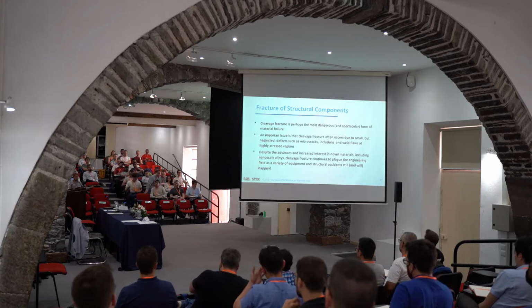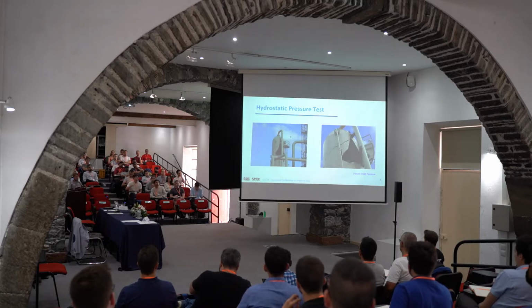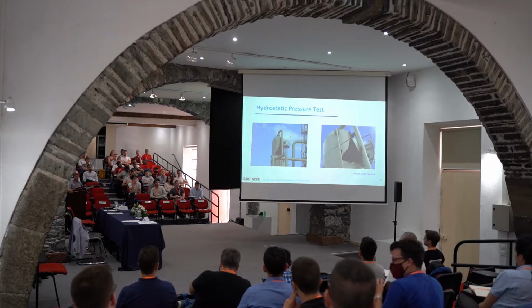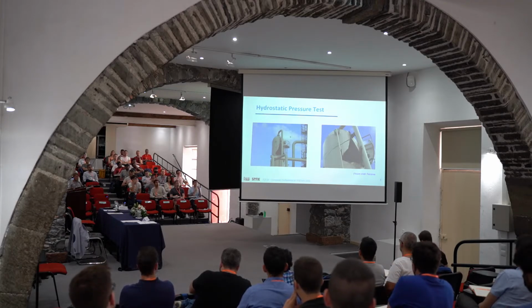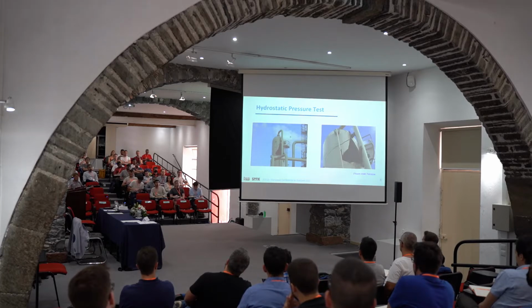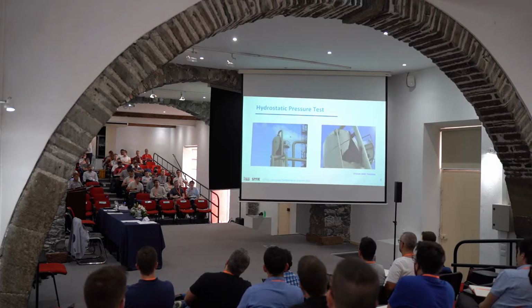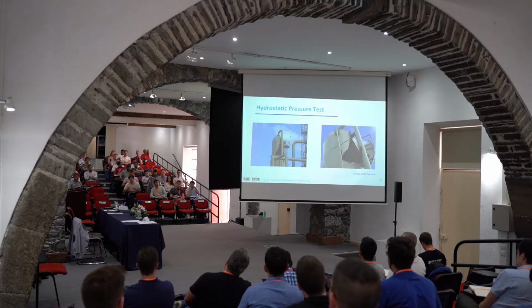Okay, and then I would like to show you a few cases. For example, this is a cleavage fracture that occurred during the hydrostatic pressure test in a pressure vessel. So you can see here, I'm not sure why my mouse is not showing here, but for you guys, I'm going to show the laser pointer here. So you can see here, this is a brand new pressure vessel. During the hydrostatic test, which is a mandatory test after the fabrication, you can see here almost no plastic deformation, which shows clear cleavage fracture, probably induced by weld defects and low temperatures.